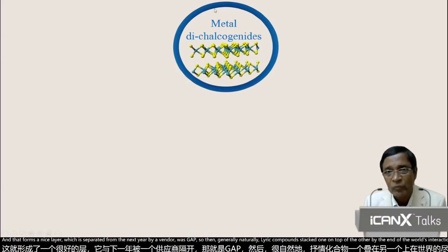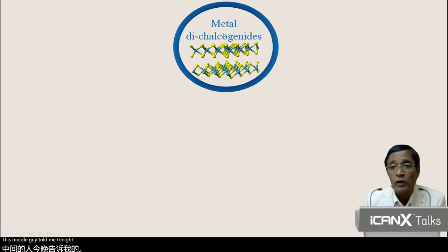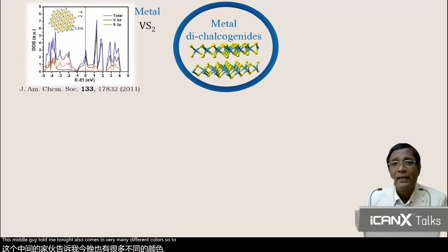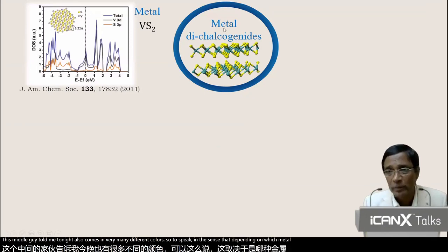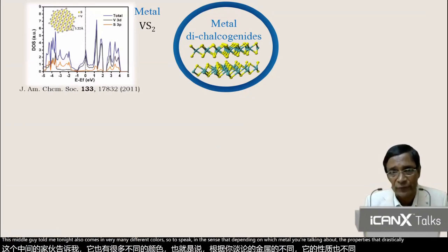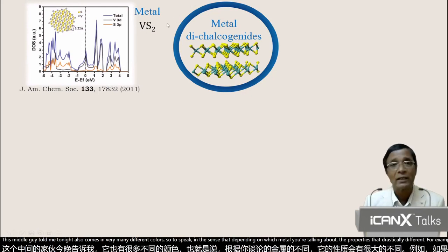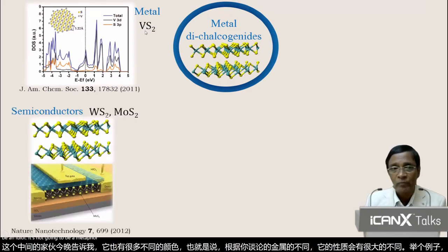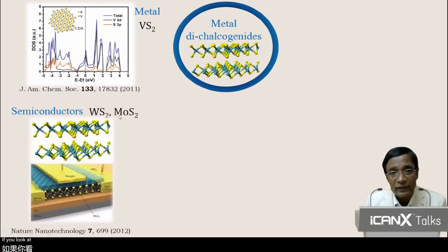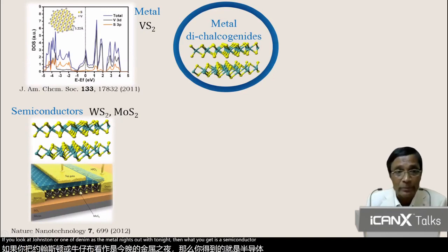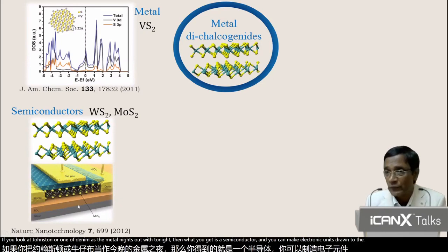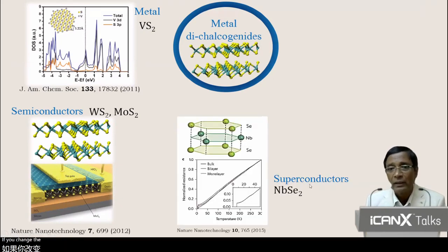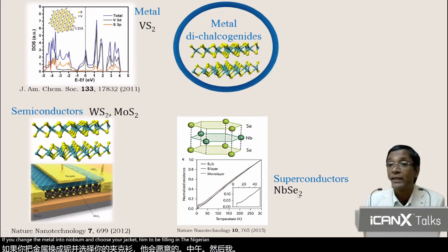So they're generally naturally layered compounds stacked one on top of the other by the van der Waals interaction between the layers. This metal dichalcogenide also comes in very many different colors, so to speak, in the sense that depending on which metal you're talking about, the properties are drastically different. For example, if you choose the metal to be vanadium, vanadium disulfide is known to be a metal. If you look at tungsten or molybdenum as the metal dichalcogenide, then what you get is a semiconductor, and you can make electronic units, transistors out of it. If you change the metal into niobium and choose your chalcogen to be selenium, then niobium diselenide is a superconductor.